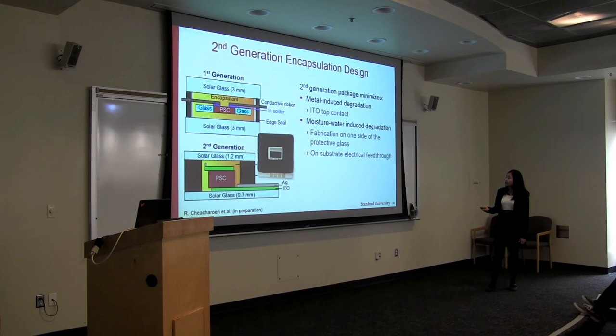Second, we try to minimize the moisture or water induced degradation because, as I mentioned earlier, I think that the moisture is getting in through the ribbon, so I tried to get rid of the ribbon. Moisture is also getting in through the trapped cavities as the solar cell moves during lamination. So to get rid of that problem, I fabricated the solar cell on one side of the glass for packaging and used an on-substrate electrode feed-through instead of solar ribbon. So we should have minimum moisture getting in.